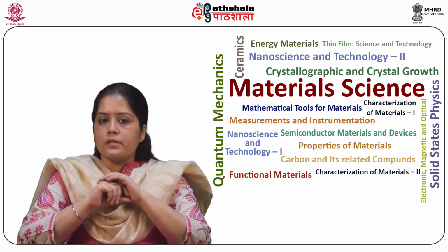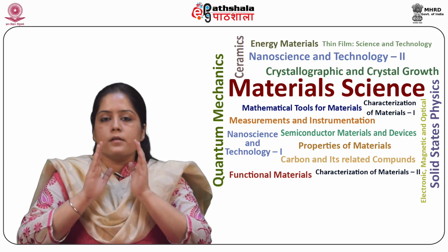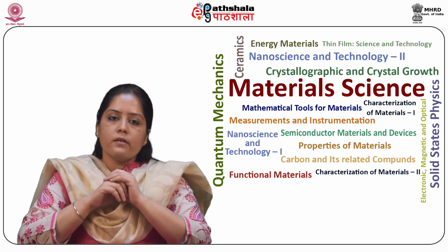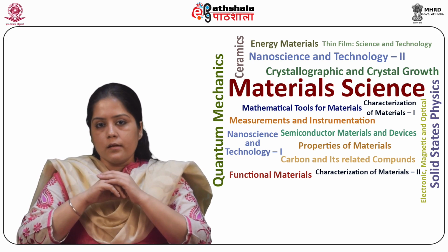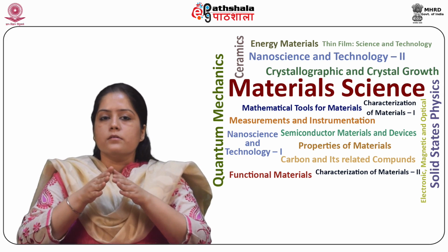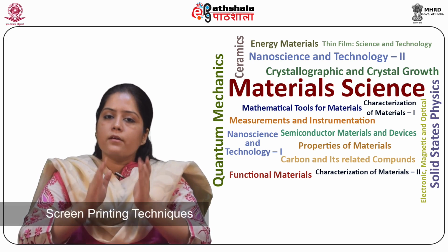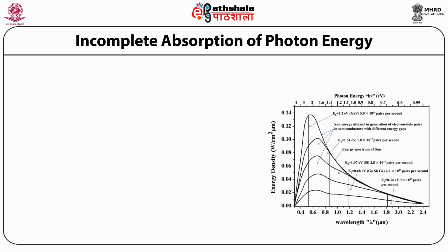Grid line widths up to 20 microns are possible using evaporation through a photolithographic technique, and up to 50 microns using screen printing techniques. Incomplete absorption of photon energy.